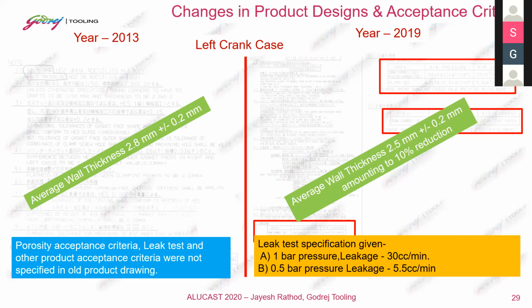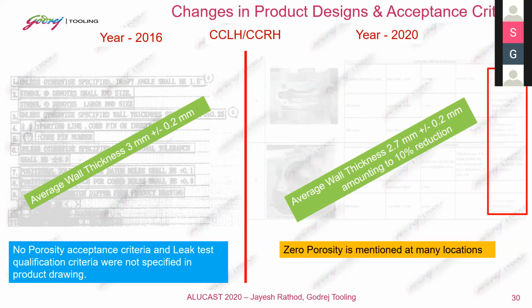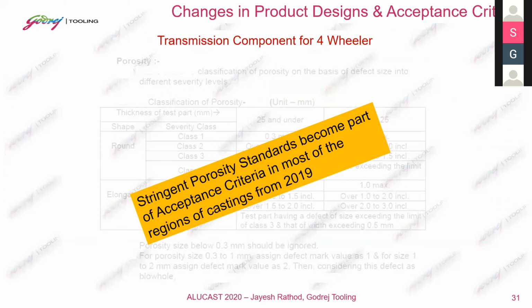Earlier, the porosity acceptance criteria was not so stringent, and it was never part of the contract. But currently, all the auto OEMs want leakage testing to be done, and specifications have been put on paper, and those are the order conditions. These are the figures of another two-wheeler maker, and here also we can see a similar story. Around 10% reduction has been planned, and a very strict norm of zero porosity in the CTQ areas has been enforced.